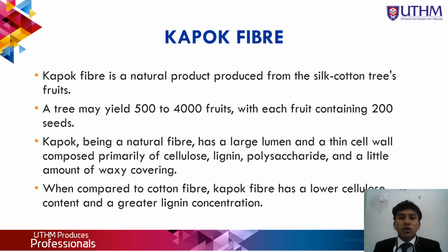Kapok, being a natural fiber, has a large lumen and a thin cell wall composed primarily of cellulose, lignin, polysaccharide, and a little amount of waxy covering. When compared to cotton fiber, Kapok fiber has a lower cellulose content and a greater lignin concentration.